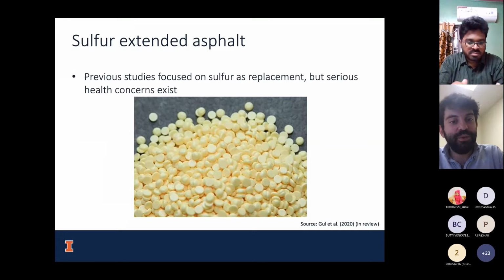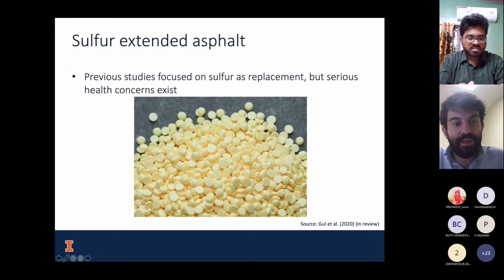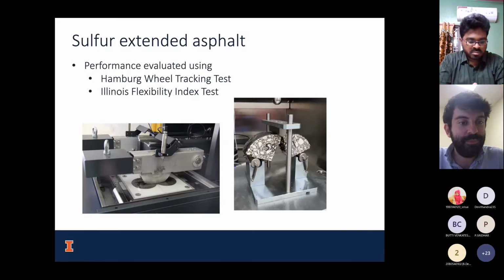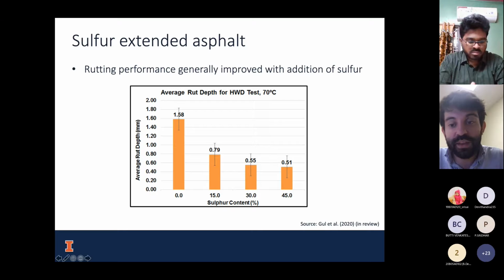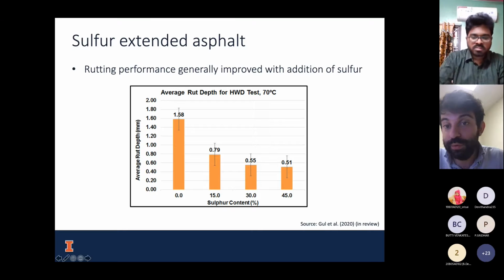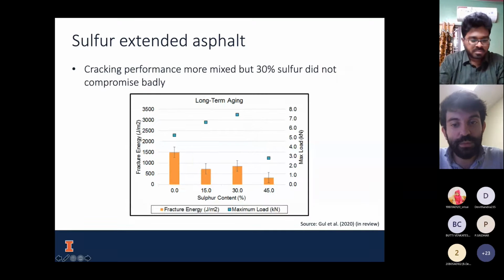So we used these kind of elemental sulfur pellets, but the problem with sulfur is that human health hazards exist from this. So this material emits a lot of toxic fumes, and again, we have to think always of the health. So we did run some tests, these tests for rutting, for example, the deformation of the pavement, that's the Hamburg wheel tracking test, and cracking test in the IFIT, Illinois Flexibility Index test. We found that the rutting is generally improved when we add sulfur. Cracking is a little bit more mixed, but generally 30% sulfur didn't compromise it too badly, so we consider that a possibility.